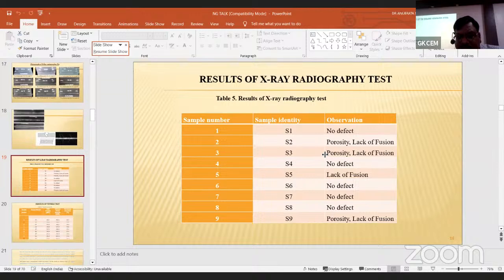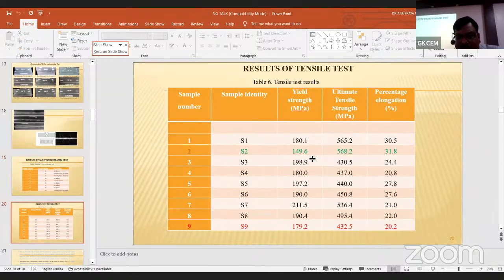This small hairline on the welded sample represents lack of fusion. And this small dot represents that some defect has occurred in the welded sample. This small dot represents the porosity that is found in the welded sample. This mainly occurs due to gas entrapped inside the weld pool. This is the X-ray radiography test result, then the tensile test result.